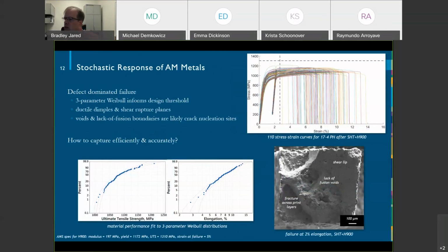And this is important because one of the things we've learned as we started looking at these materials is, people ask lots of questions about whether additive material is as good as wrought or whatever. My answer is always it's different, right? So if you think about a wrought material or a casting or a forging or a heat treat or a rolled material, they all have different properties. And a lot of what we've been doing is trying to understand and quantify those materials. And so here's some early data on 17-4, which is actually a relatively poor material at this point.